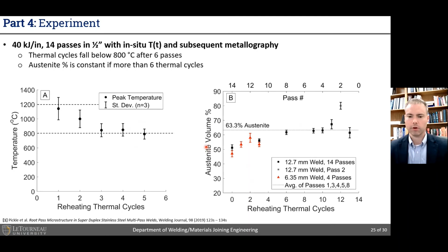Now, we then took a cross-section of that and we did the austenite volume fraction characterization as a function of the pass number. So, for example, pass 0 would be the root pass, and it corresponds to 14 reheating thermal cycles, while pass 14, which would be the cap pass, would correspond to the as deposited. So first, let me highlight the black.